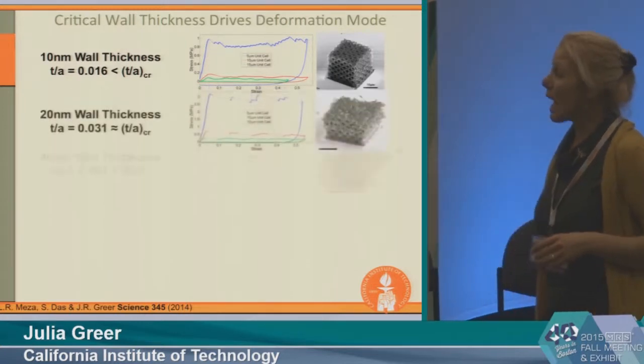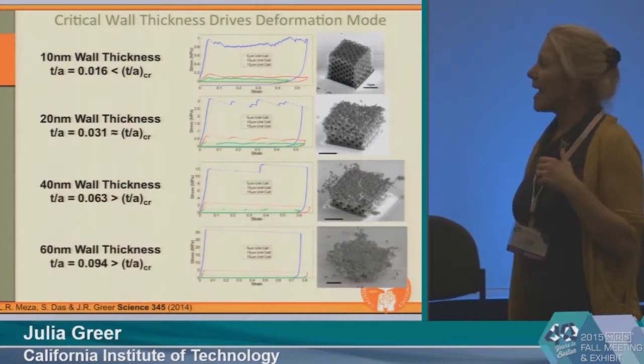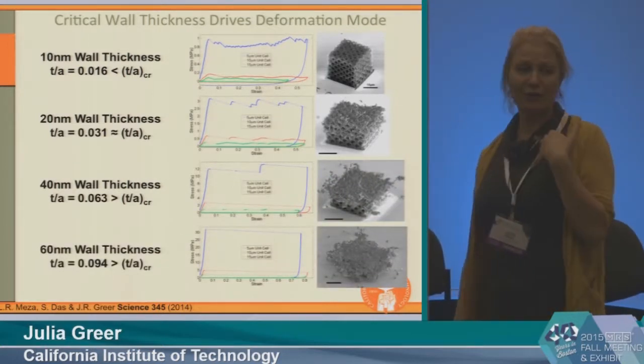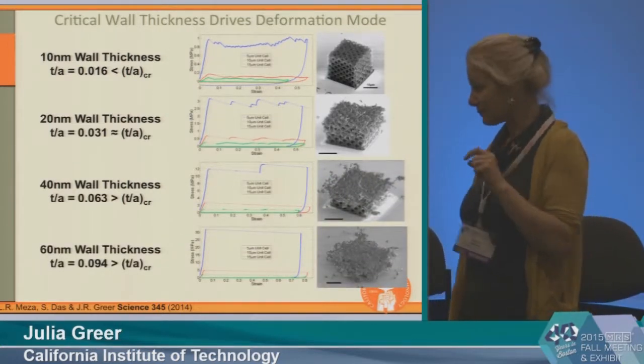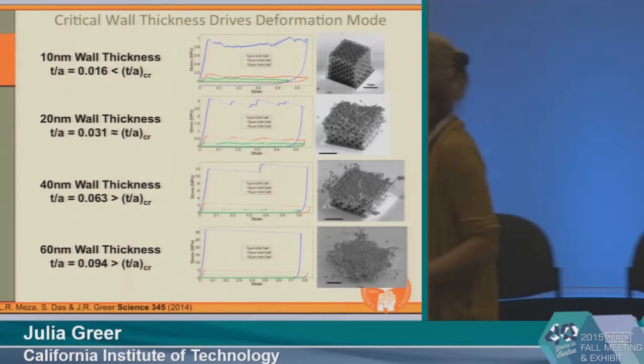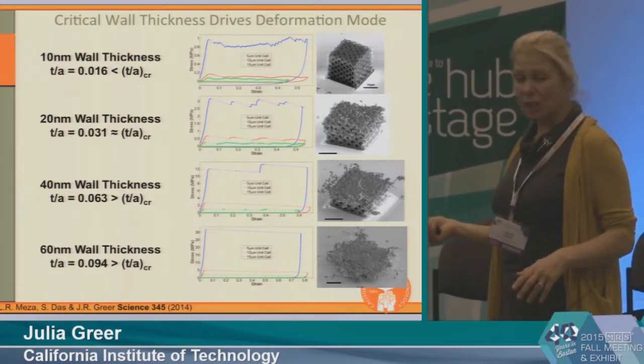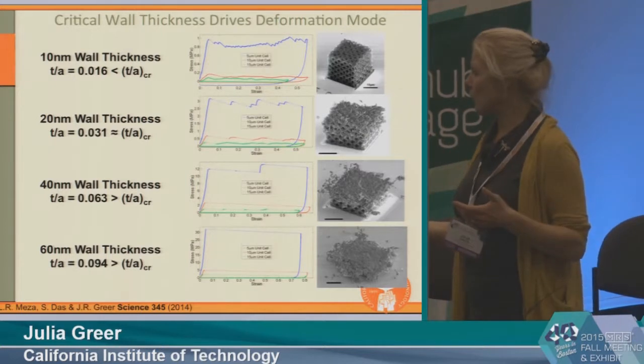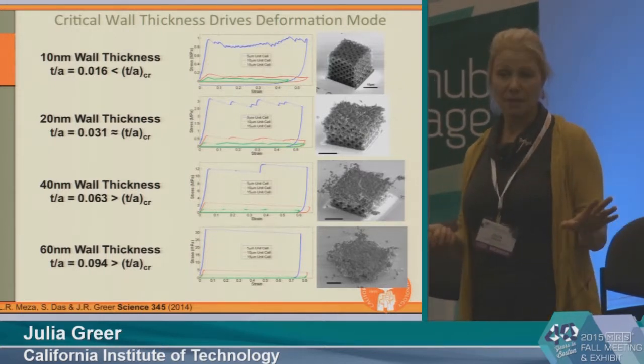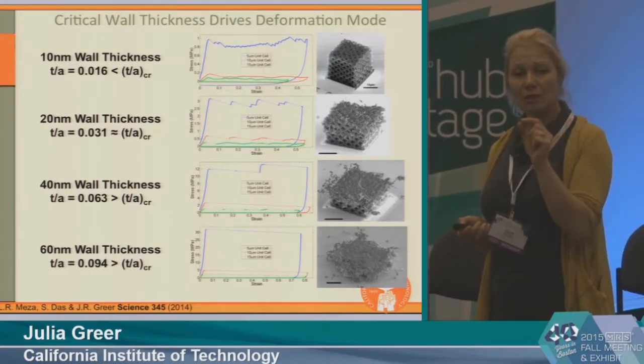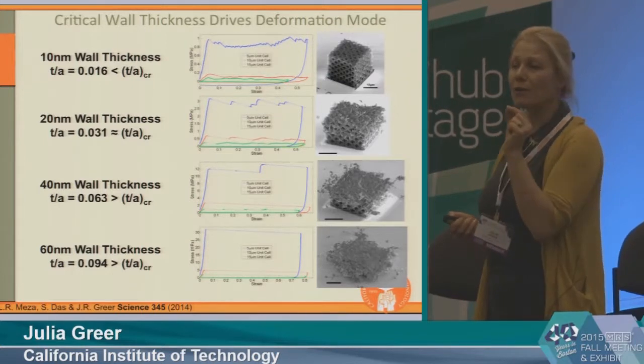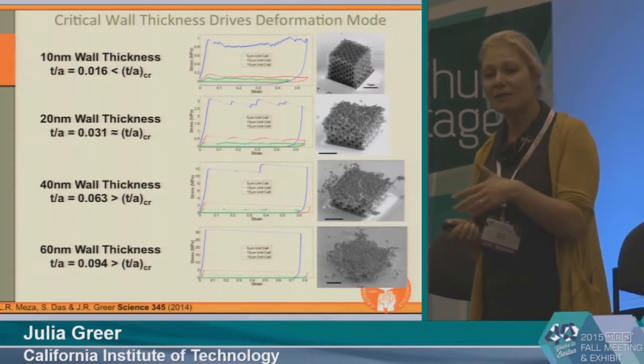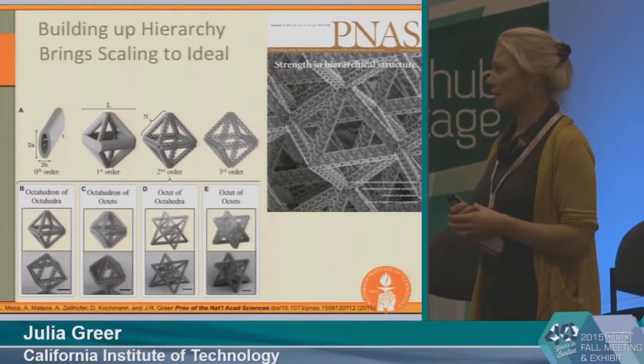Now let's see what happens as you increase the wall thickness. And you can see as you deviate farther and farther from this critical ratio of the wall thickness to the radius, your deformation becomes a lot more jerky, much more stochastic, up to the point where there's not even an attempt at recovery. So this is what's important. It's important that we really understand these materials both from the material and from the structural perspective.